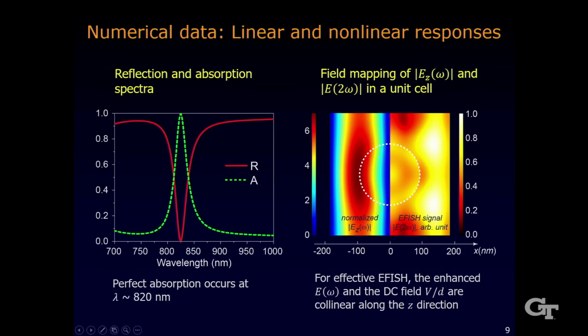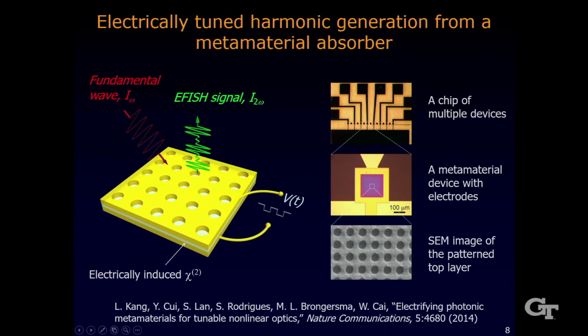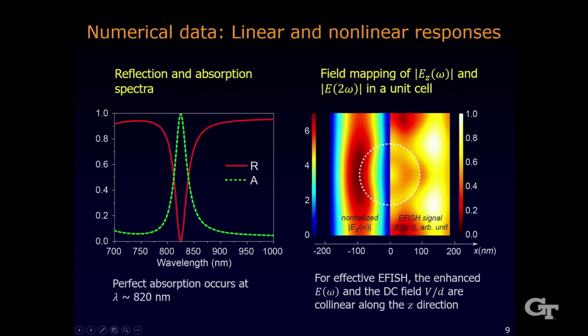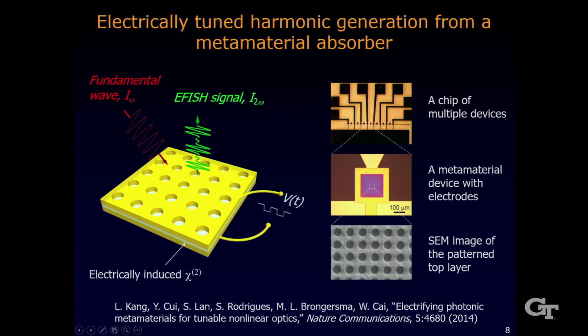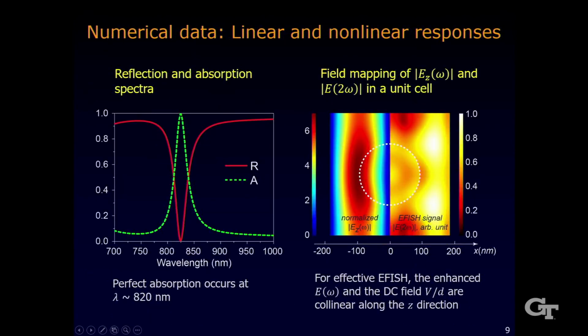More importantly, by analyzing the component of light, you can see in the gap region, all the fields, including applied field and the optical field, are collinearly aligned along the z direction, that is the direction perpendicular to the stacks. This is the preferred configuration for efficient generation because in this case, we can make use of the most pronounced element in this Chi2 tensor.